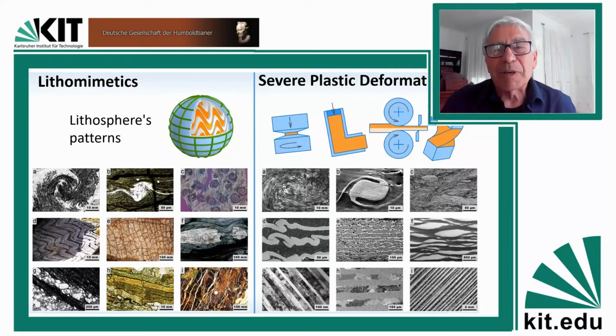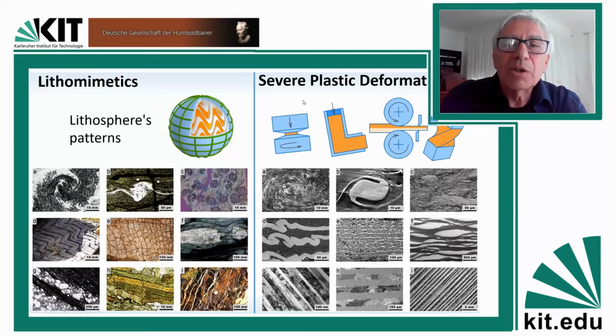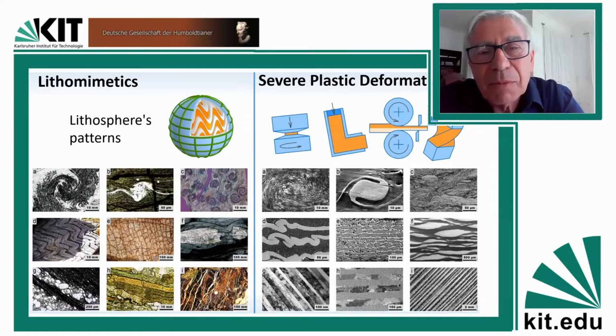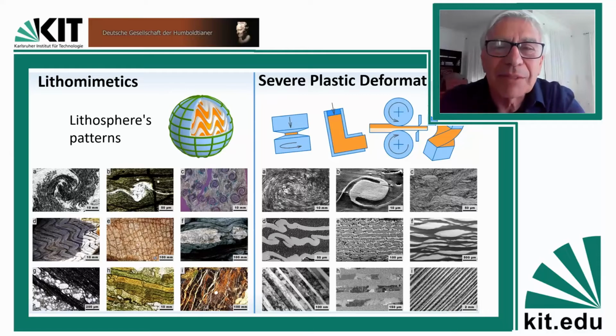Fortunately, there are experimental techniques in metal forming that can produce structures which are similar to those of lithosphere. The whole range of severe plastic deformation techniques, and some examples are shown here, produce those structures. One is the high pressure torsion, the technique where you deform a little penny-shaped specimen between two anvils under high pressure, vertical pressure here, several gigapascals, and you rotate those anvils. The technique goes back to Bridgman, and it's quite popular in the materials engineering community.